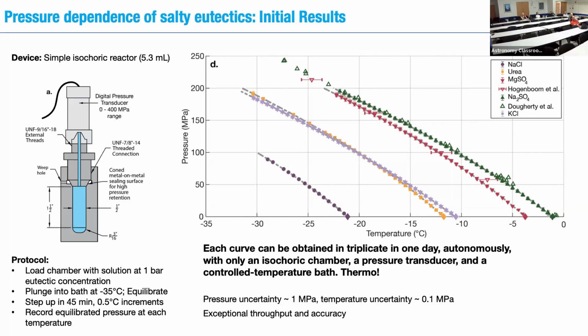So you almost can't even see the error bars on these markers, but the error bar we get with the isochoric freeze-melt technique is about plus or minus 1 MPa. When you look at conventional high pressure diamond anvil cells with optical evaluation techniques, you're usually looking at plus or minus 10 to 20 MPa, right? You look at the size of these error bars from some of the really seminal work in this field, and it shows us that this isochoric freezing technique, by leveraging very simple thermodynamic tricks in the system, can yield really high accuracy temperature and pressure measurements of the eutectic curve.